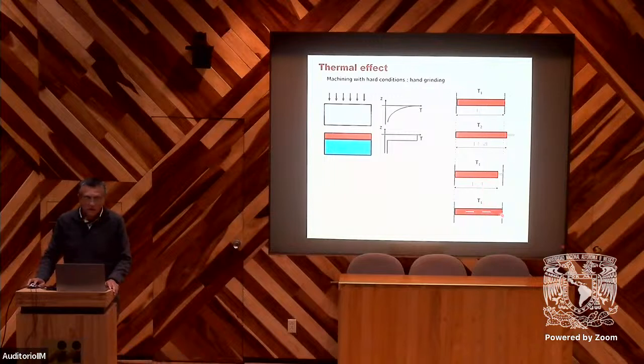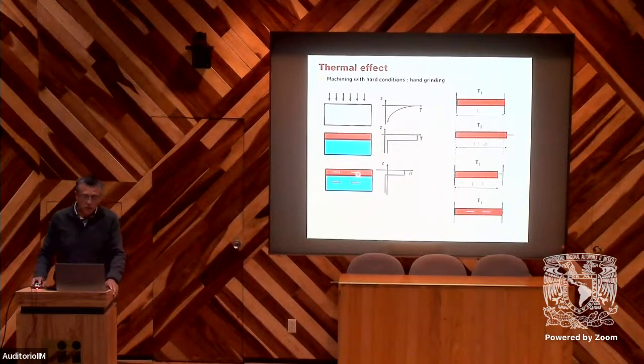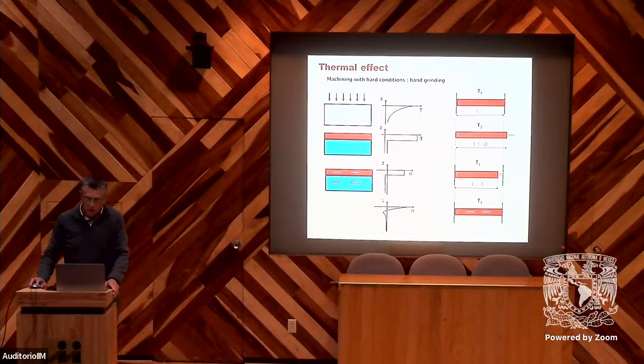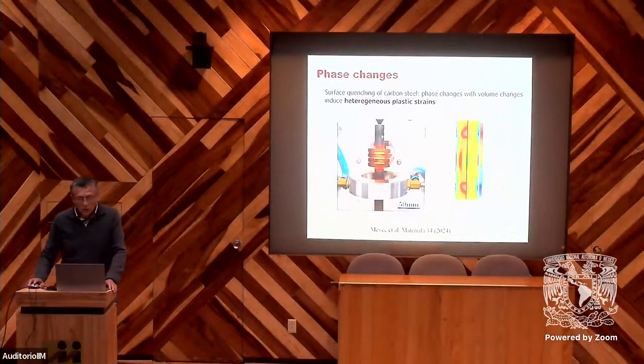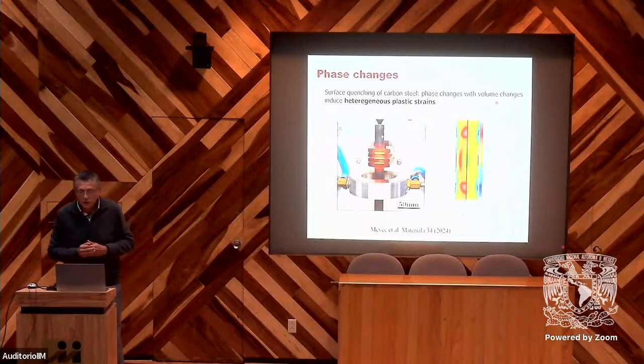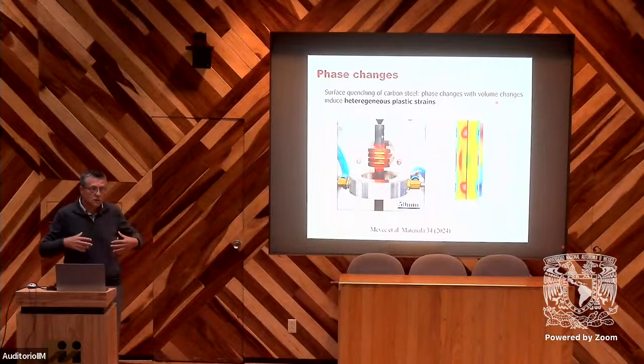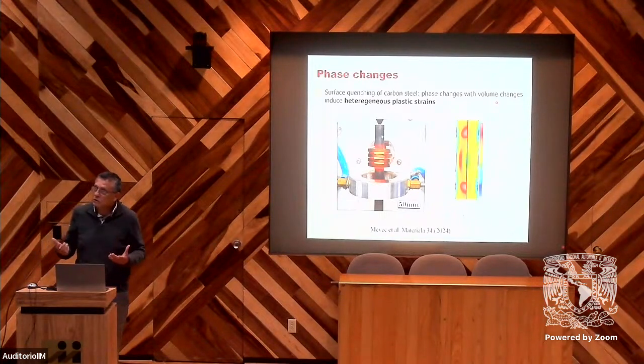That means this part will be in tension. So the thermal effect will induce tensile residual stresses near the surface, and this will be equilibrated by compression inside the material. Of course, with the continuous gradient, we will have such a profile with tensile near the surface, equilibrated by compression inside the material. We can also add the phase changes effect. In this case, we need to consider the volume changes, and sometimes, for example, when we have a surface quenching, we have these changes only near the surface, and there is no phase change inside the material, so we can induce plastic deformation, and we also get residual stresses.